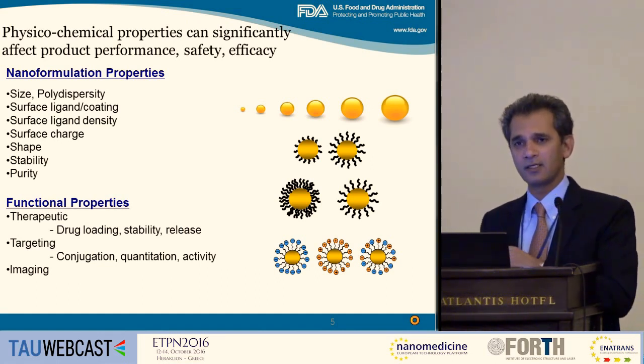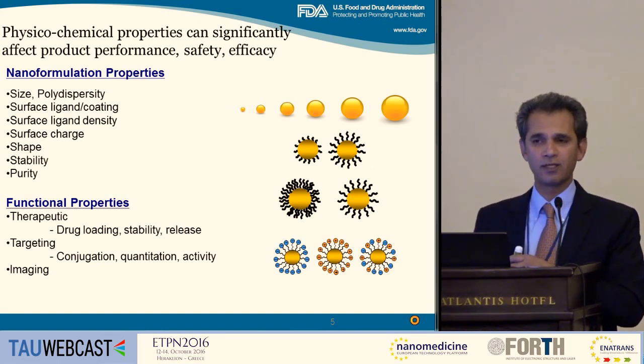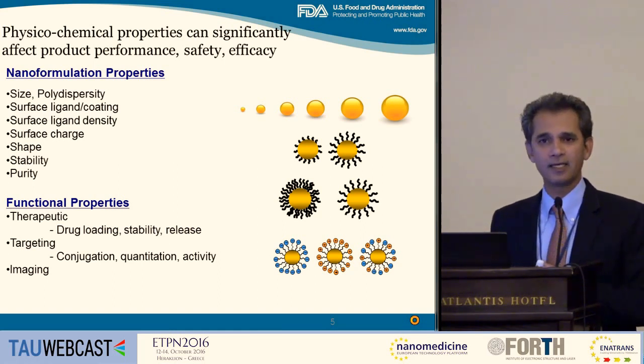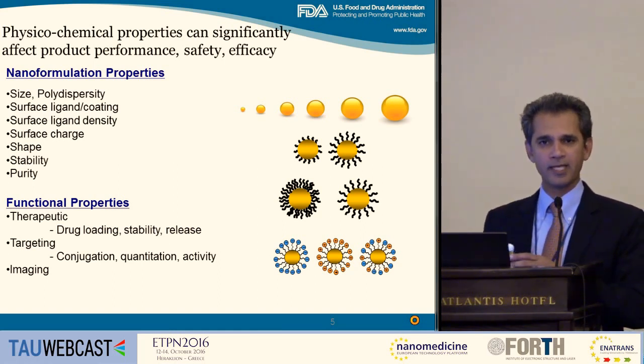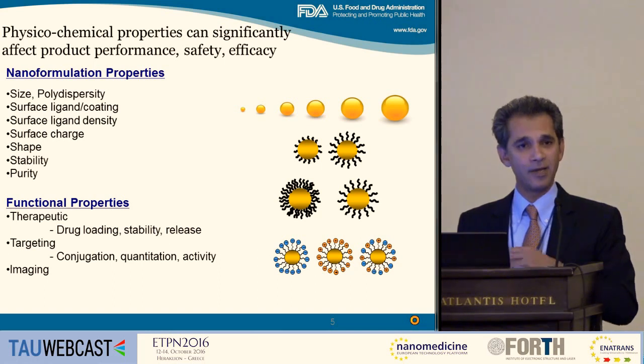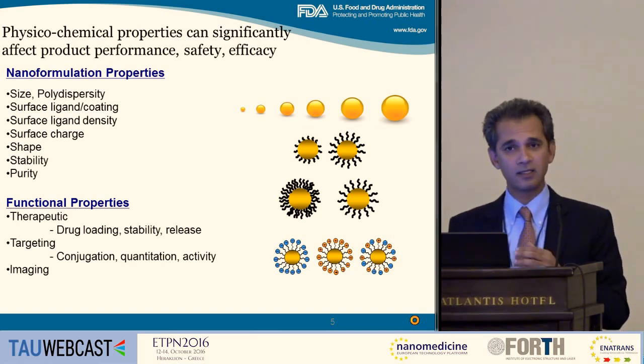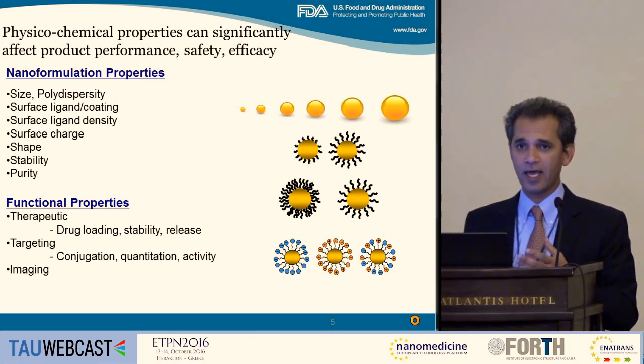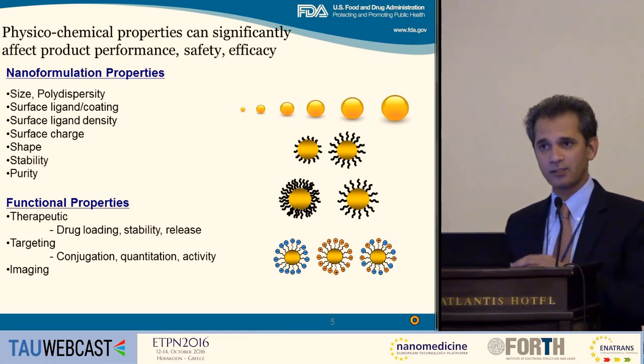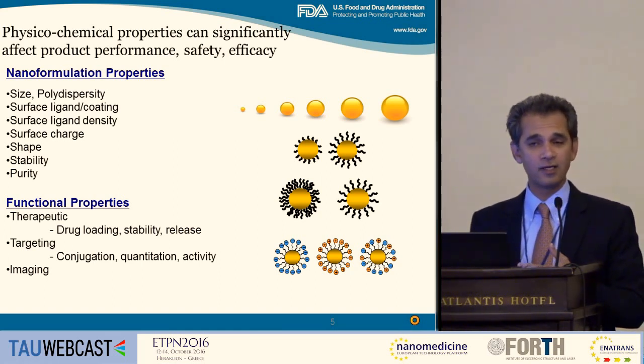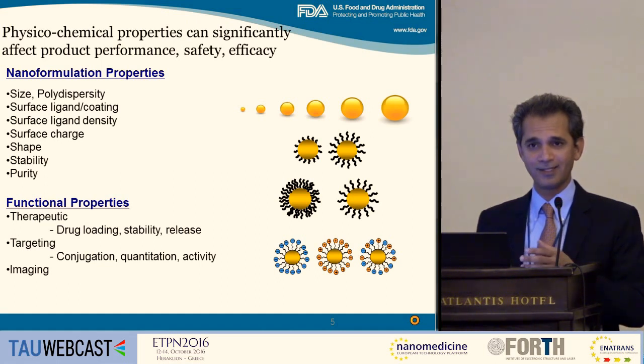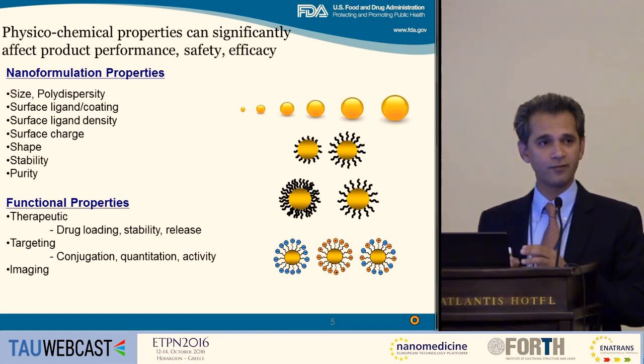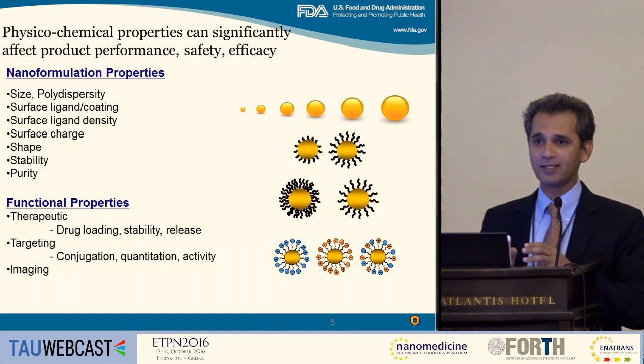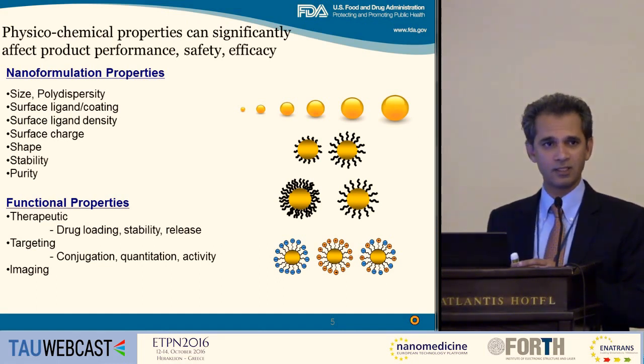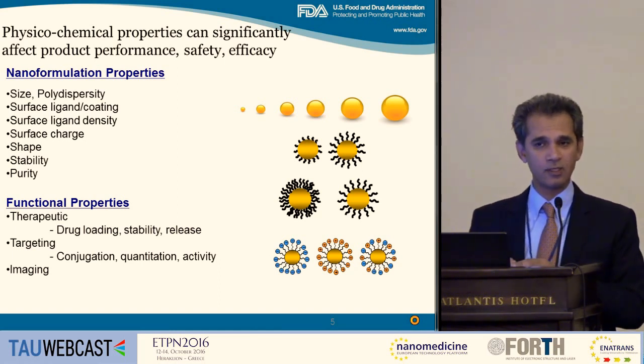In other words, if you take a nanoparticle coated with, let's say, polyethylene glycol or some kind of polymer to passivate the surface, depending on how much polyethylene glycol is on the surface, you can change the pharmacokinetics of the product. You can change the biodistribution. You can change the safety and efficacy of the product. So defining how much of the coating material you have, defining the composition of the coating material, defining the polydispersity, inhomogeneity, heterogeneity of the coating material.